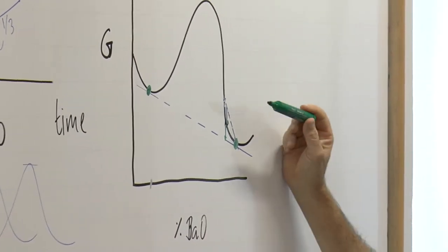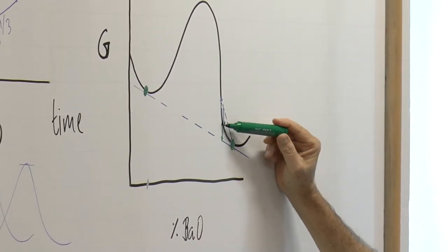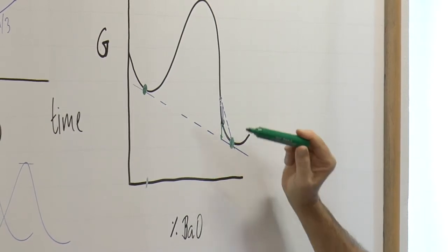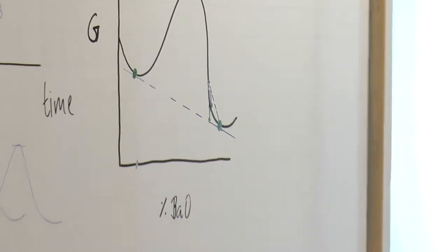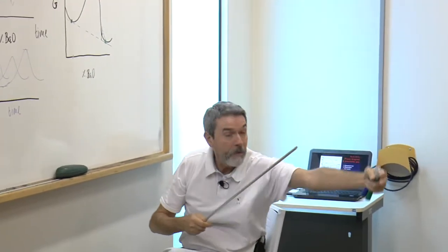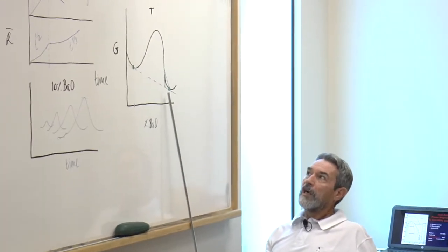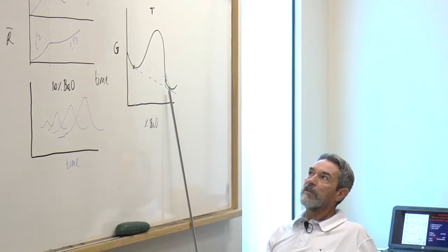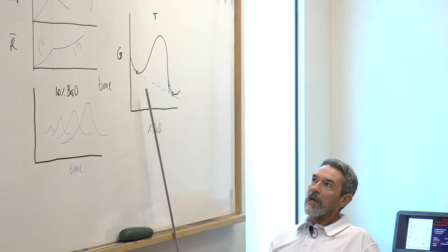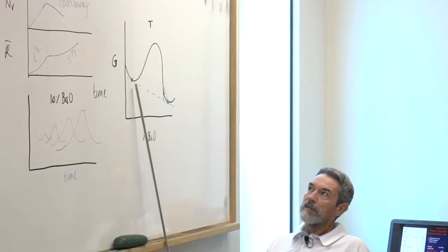The free energy now has decreased. That's why we need a large fluctuation to decrease the surface energy. That's why the composition of the particles is far away from the composition of the starting glass. The starting glass, remember, was here, in our case, 27% of barium.